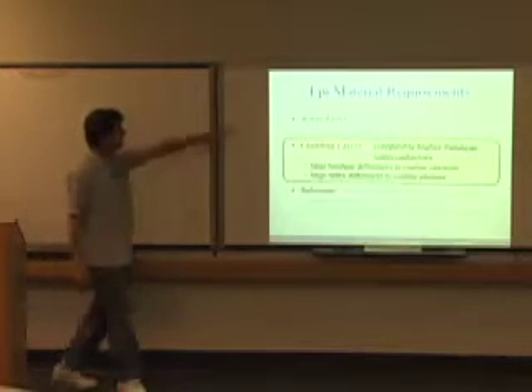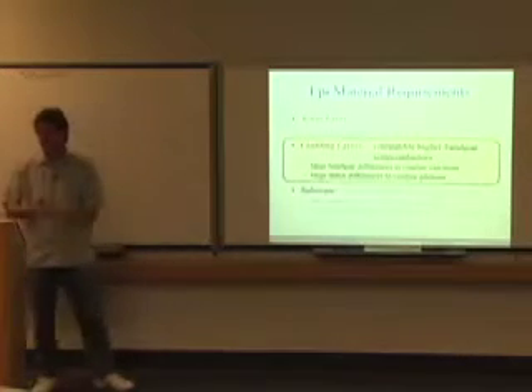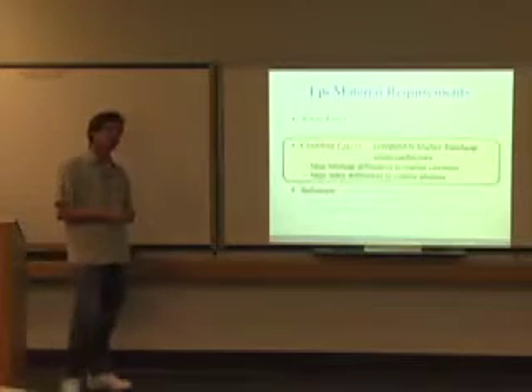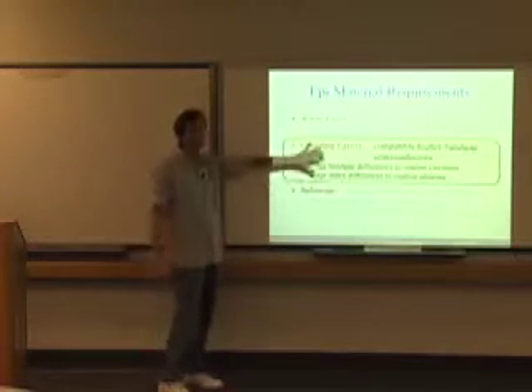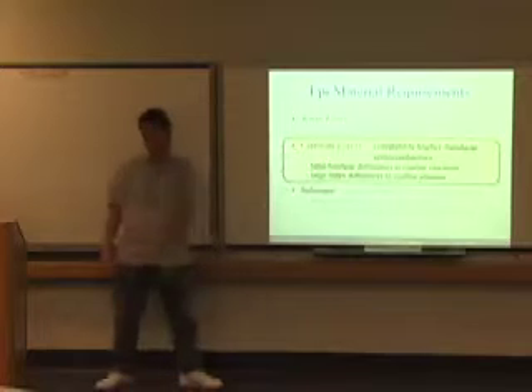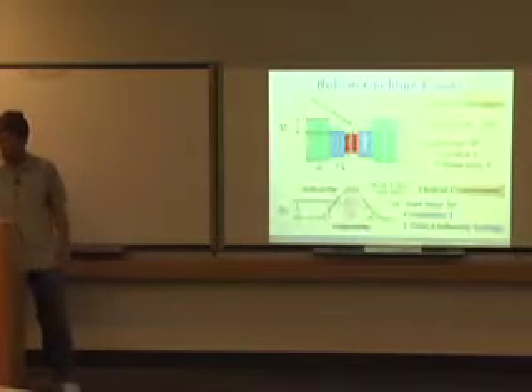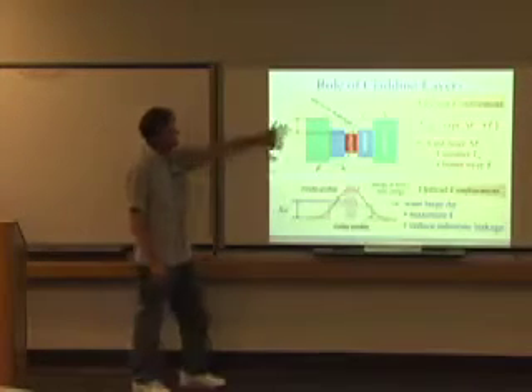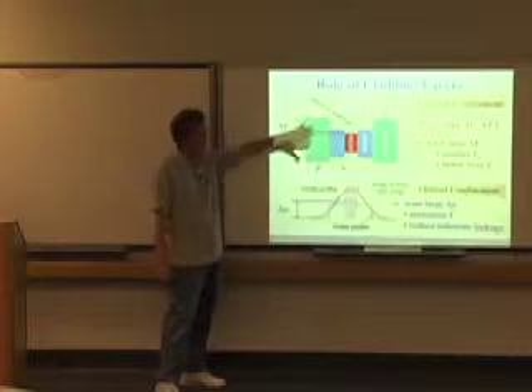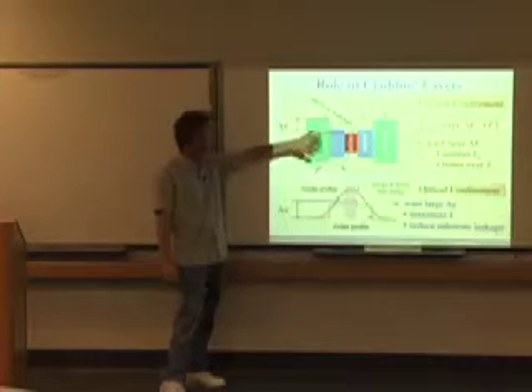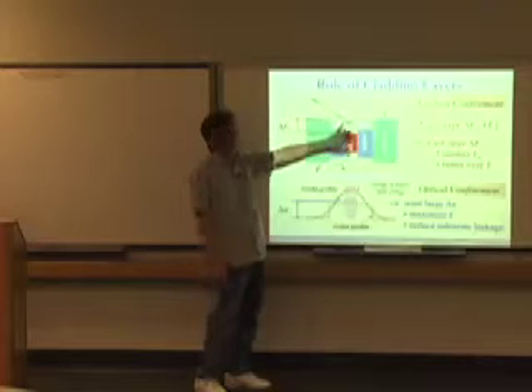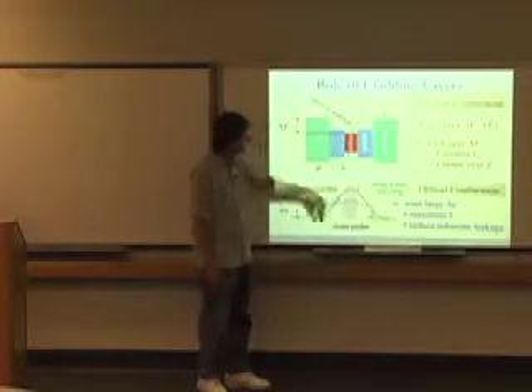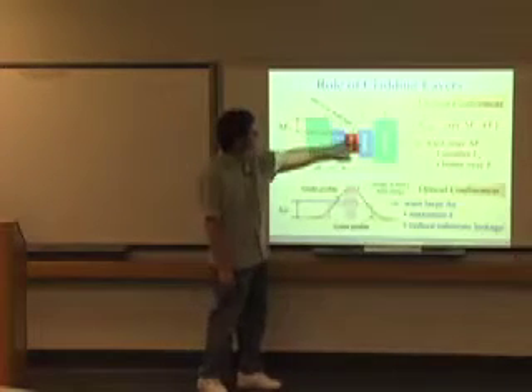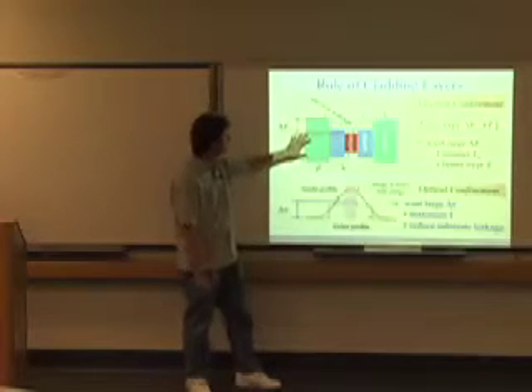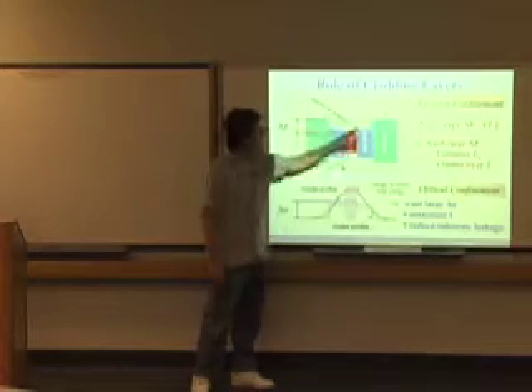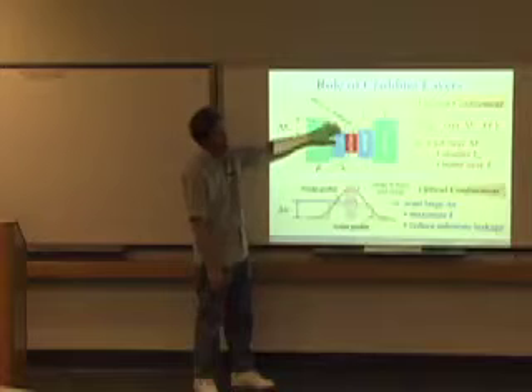So an additional thing that you need is cladding layers. You need a compatible higher bandgap semiconductor. And this is something that's a little different than with LEDs. With LEDs, you don't need to worry about this so much. But for lasers, you need to have really good electron confinement because your carrier densities are very high. So you really want to keep those electrons in the active region. So usually you have an active layer with barriers on either side and then a cladding on either side of that. And you want to dump electrons into the active region, but you want to prevent them from leaking out.